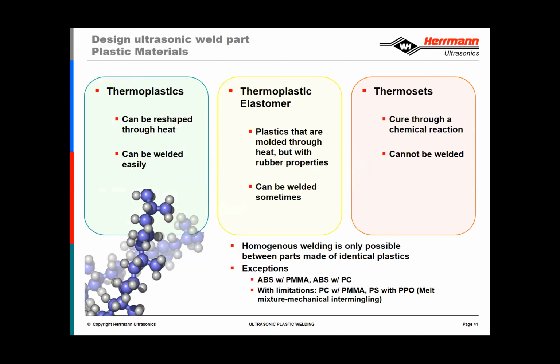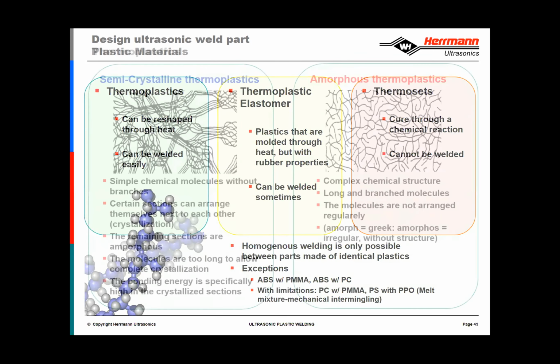And furthermore, homogeneous welding is only possible between parts made of identical plastics. So we're talking about welding ABS to ABS. However, with the case of ABS and acrylic, there is compatibility between them, as well as ABS with polycarbonate. And then with some limitations, polycarbonate with acrylic and polystyrene with polyphenylene oxide or PPO. This really depends on the melt flow index and the processing temperature of the materials. And we'll be getting into that a little bit further later.